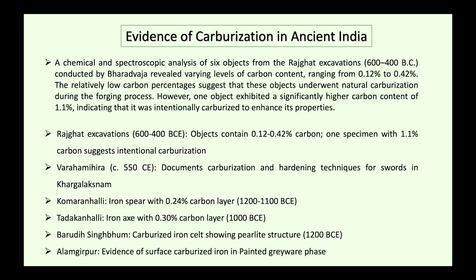In this technique, a chemical and spectroscopy analysis of 6 objects from the Rajghat excavation, dated 600 to 400 BCE, conducted by Bharadwaj, revealed varying levels of carbon content ranging from 0.12 to 0.42%. The relatively low carbon percentage suggests that these objects underwent natural carburization during the forging process. However, one object exhibited a significantly high carbon content of 1.1%, indicating that it was intentionally carburized to enhance its properties. So the carburization process is very important for getting much harder iron.